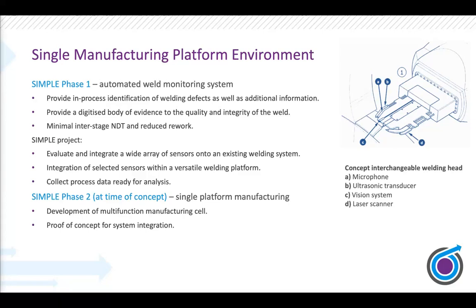When you're performing thick section welding for pressure vessels, because there's so much uncertainty around the defect rates of the process and the high cost of finding flaws late in the process, it's very common to do what's called interstage NDT. So you're not performing a final inspection, but an inspection partway through the weld. Say you deposit 10 to 20% of your fill volume. You then pause the process, cool it down, move it to an inspection area, and take your volumetric inspection. If there aren't any flaws, you can bring it back to your process, bring it back up to temperature, and carry on. Or if you do find flaws, then it has to be sent to a rework area.